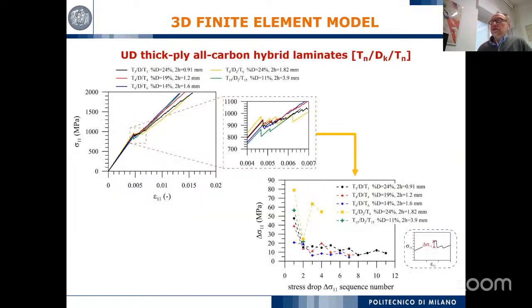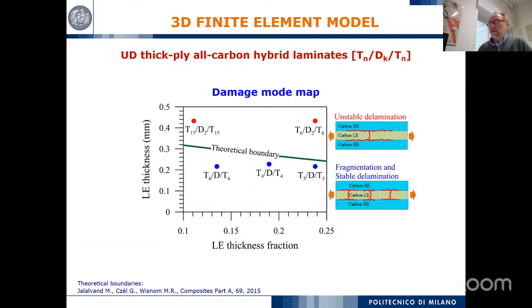Even also for this thick ply laminate, we performed several stacking sequence analyses, and this led us to understand when we can distinguish different damage evolution, and to create this damage mode map. And so having a model like this that can be extended to different stacking sequences with different orientations is interesting, because in some way we can create this damage mode map, and so we know in the design process of the material which stacking sequence and which content of low elongation